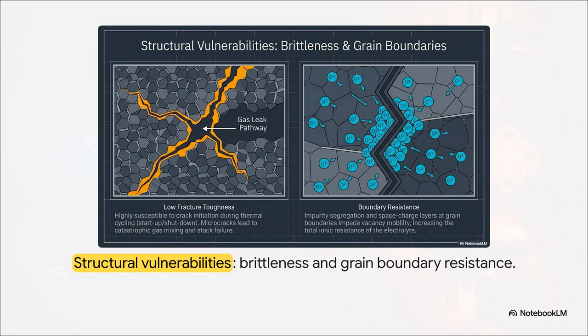This extreme environment exposes severe structural vulnerabilities. For one, there's the constant threat of low fracture toughness. Basically, at its core, it's a brittle ceramic. So the simple act of thermal cycling from starting up and shutting down can cause microcracks, which then turn into catastrophic gas leak pathways. On top of that, we have grain boundary resistance, where impurities inside the material act like roadblocks. They literally impede the flow of ions and jack up the total internal resistance of the cell.